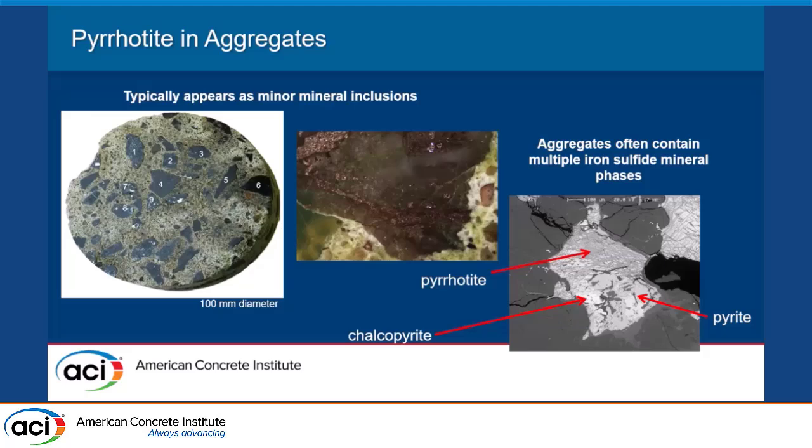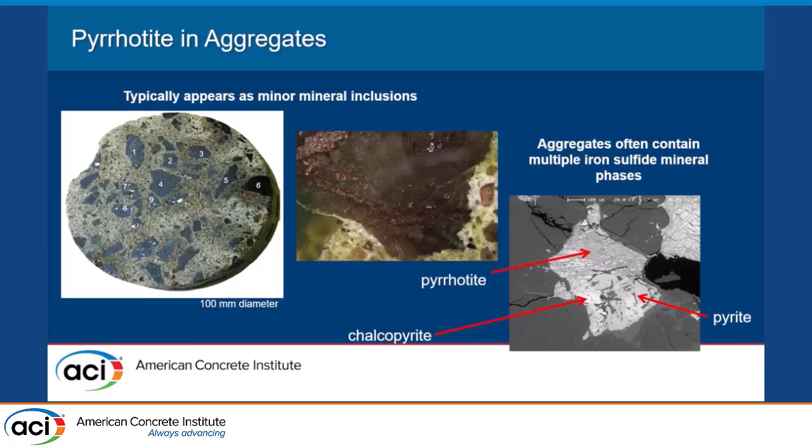So they used the total sulfur amount, and then what we did was, for all of the coarse aggregate, because that was the aggregate in question in this case, we scanned the sample and numbered every aggregate. Then for each of those aggregates, we did a visual assessment to see, okay, it's taking up about 3% of that one aggregate grain, or maybe 0.5% of that aggregate grain.